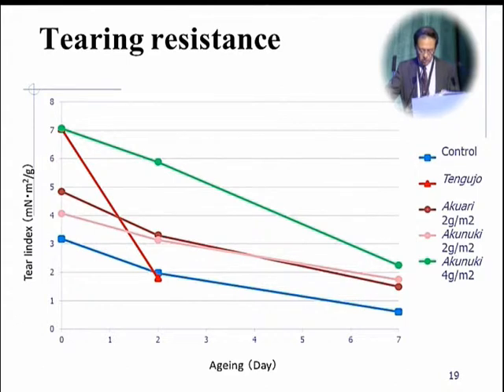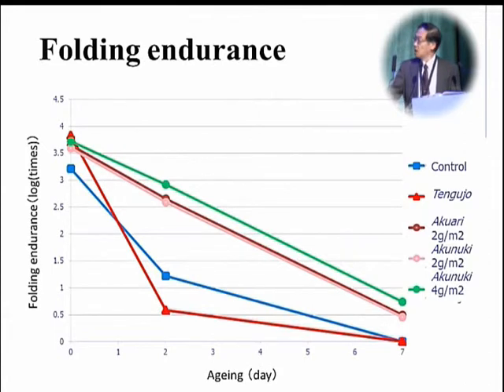This is due to an error in the selection of methylcellulose. The paper becomes stiff after treatment, and it was not possible to measure the tearing resistance after day 2. Similar results are observed in terms of folding endurance. The difference between the thickness of the kozo fleece layer, 2 and 4 grams per square meter, is not as obvious as with tearing resistance.